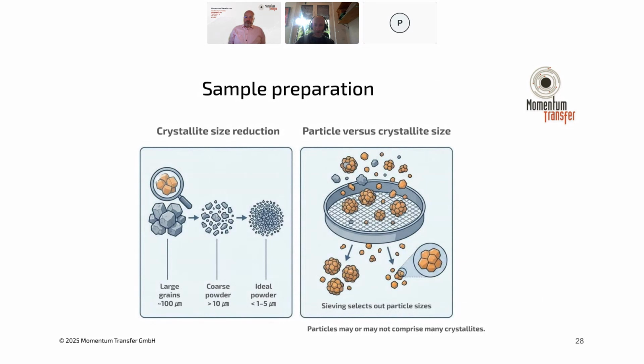A further point is that crystallite size reduction is really important to get good data. Typically you really want crystallite sizes in the 1 to 5 micron range to avoid these more significant microabsorption or particle orientation biasing effects. So typically you grind your powders down and micronize them to do that.